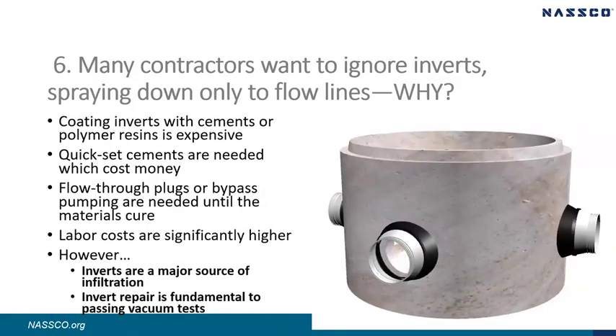Point 6 is, there are those who want to seal the manhole down to the flow line, but avoid coating the invert. Why? Coating inverts with cements and/or polymer resins is expensive. Expensive quick-set cements are usually needed. Flow-through plugs and/or bypass pumping is needed in order for the materials to cure, and labor costs are significantly higher to coat the inverts. However, inverts need to be coated because they are a major source of infiltration. Secondarily, invert repair is fundamental to vacuum testing. No invert repair, no vacuum testing.